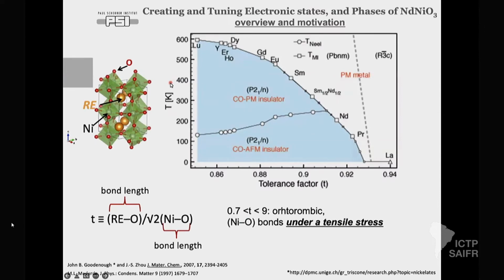So coming back to the topic. So as I said at the beginning, if you have a system which shows phase transformation, this system is already a very good candidate for quantum devices. For example, nickelates show metal insulator transition, which is what you can see here. Here is the paramagnetic metal, and when you are lowering down temperature, depending on the elements which are there, you will go to the charge ordered paramagnetic insulator or charge ordered antiferromagnetic insulator. You have a very good platform to use it for potential applications.